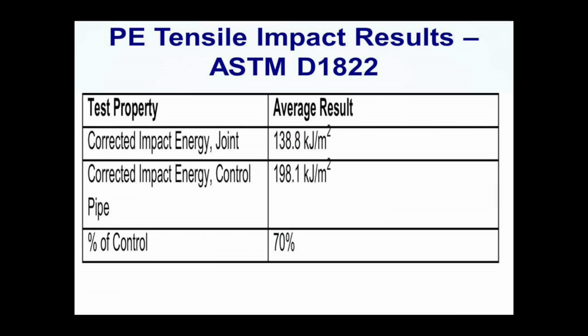Again, we want to look at the energy to break and compare it to control. These are the energy to break values for the butt fusion joint and the control pipe. In the case of polyethylene, it's 70%. This is a very common test method — in fact, probably the best test method to use for butt fusion joint integrity. The typical industry guideline is between 50 to 100% is a good butt fusion, between 25 to 50% is a marginal fusion, and below 25% is a bad butt fusion. So 70% is a good value.